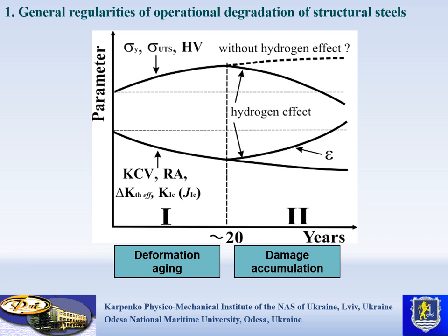General regularities of operational degradation of structural steels. It is well known that long-term operation causes in general a degradation of mechanical properties of structural materials, including steels, in comparison with the as-received state. A long-term static loading, as a rule, is dangerous under the action of aggressive environments, and regarding cyclic loading, it is especially a strong factor for steel degradation. These aspects are superimposed on the features of operational degradation of rolled steels.